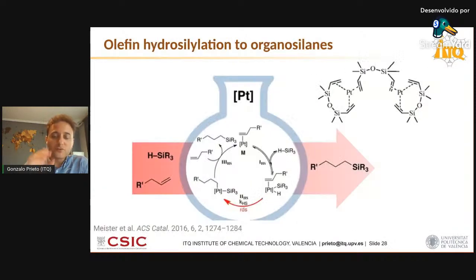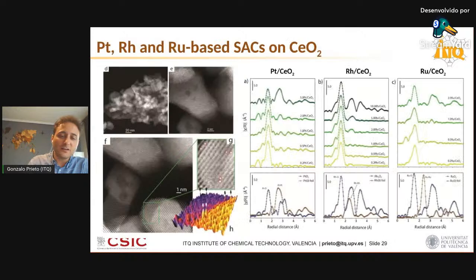So again, the idea was to try to find an alternative to this system based on single atom catalysts, and that's why we decided to synthesize now not catalysts based on one single metal dispersed atomically on different oxides, but on the contrary, different metals, platinum, rhodium, ruthenium, dispersed atomically in all cases on a common support material, ceria in this case. And again, you need to trust me, in view of time, I cannot discuss the results in more detail, but you need to trust me that we did everything that we had to do to confirm the monoatomicity of these metal centers, at least at this close to one atom per square nanometer surface metal content on ceria for all different metals.